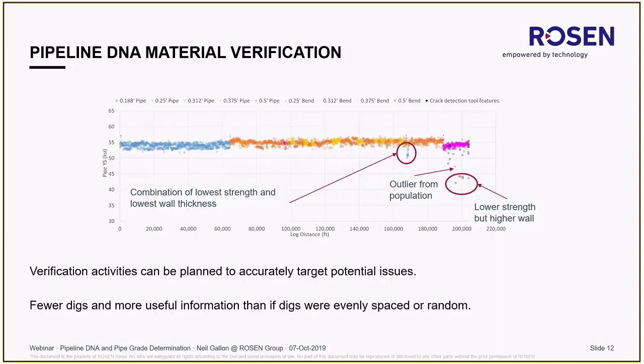However, there is another area at about 170,000 feet log distance where you have both the lowest strength and the lowest wall thickness. That is going to be the area of highest risk for a pipeline operator, and where they need to concentrate their verification strategy. So you can target your efforts to accurately target where the potential issues are.